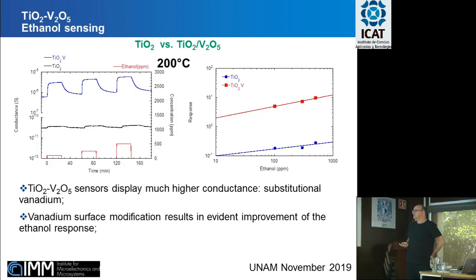Very fast, some ethanol sensing, we could see that by adding vanadium, we had an increase of the response of the sensors by almost 100 times, almost two orders of magnitude. So the initial concept, again, was satisfied, and it worked. It seemed that we deposited some vanadium onto the surface of titania, and it works very well.